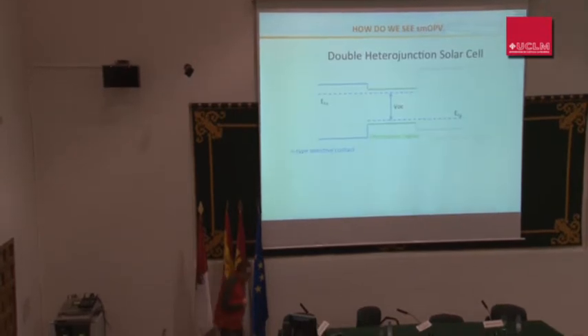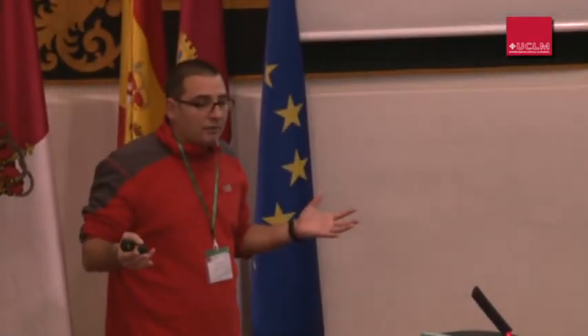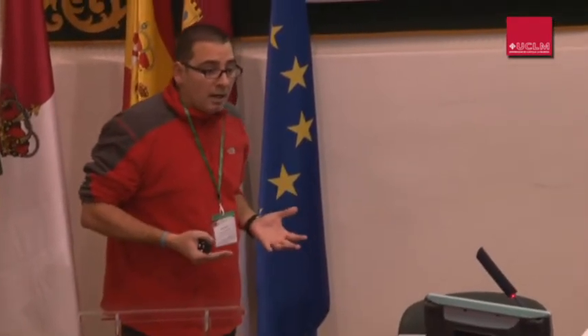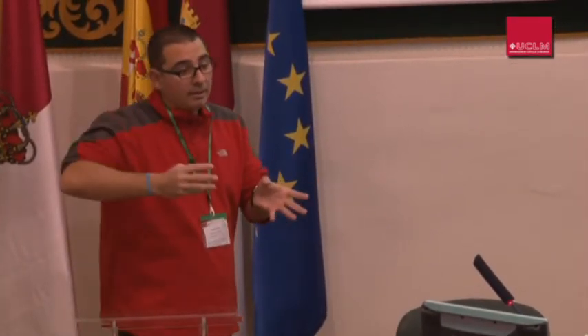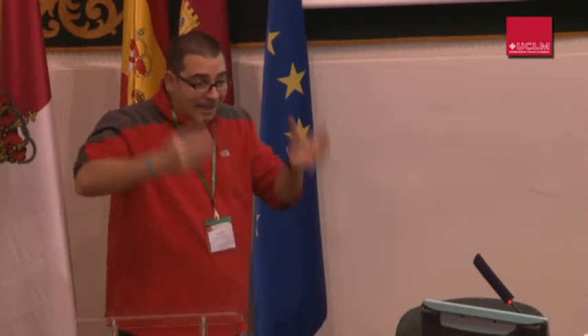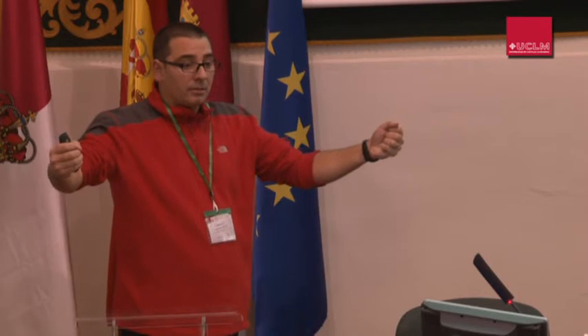So what is our picture? And this is quite special because we are only a few groups in the world that believe that this is possible, and now we're getting a lot of emails from people who believe that everything we have said in the papers in the last years is true, and some people even get influenced by these ideas to make very good solar cells, including in silicon. The picture is, imagine that you don't have electric fields, because most people in the solar cells field came from silicon, and they thought that when you put two metal contacts, you create an internal electric field that has to take apart the exciton.